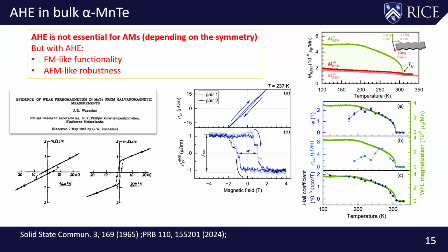Tn for this system is 300 Kelvin. It only appears in a very narrow temperature regime below Tn, and then it disappears at low temperature, which again is very strange, right? If it's a simple ferromagnet that gives rise to the anomalous Hall, you should expect any magnetic moment to persist at low temperatures. If impurity magnetic moments give rise to anomalous Hall, it should also persist at low temperature. There's no reason why it should disappear, but it actually disappears at low temperature. So what is actually going on is not understood at all.